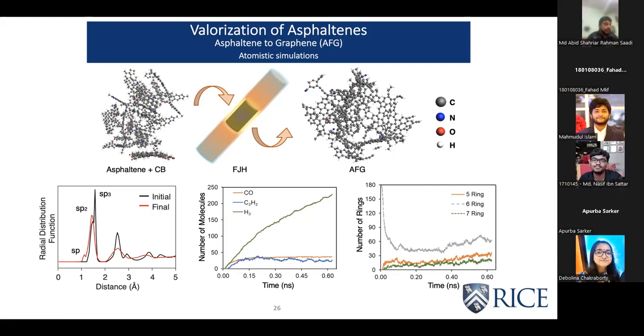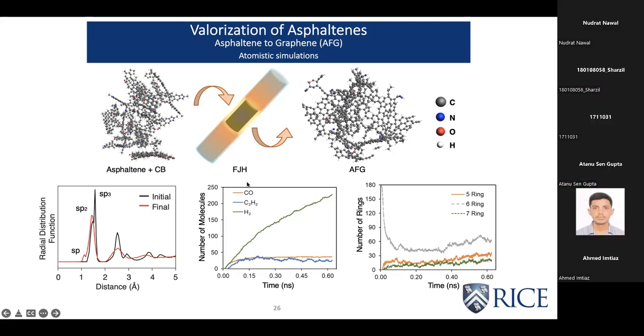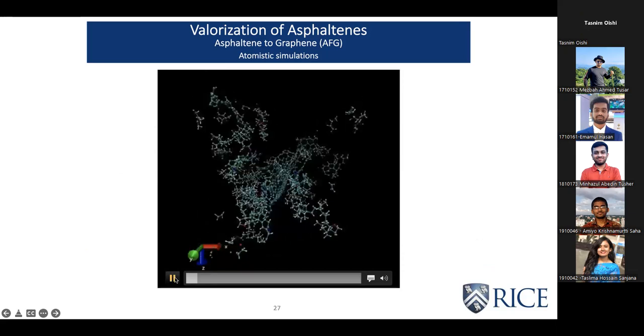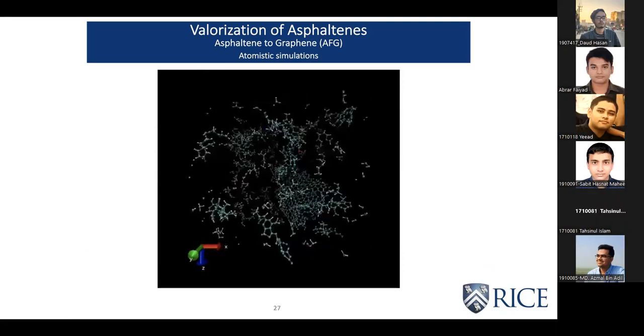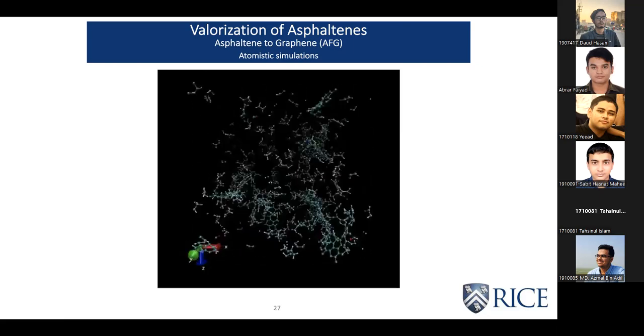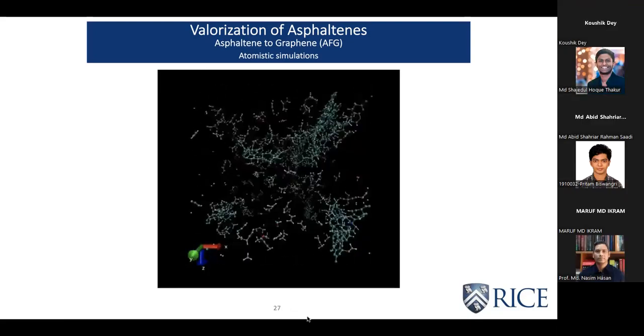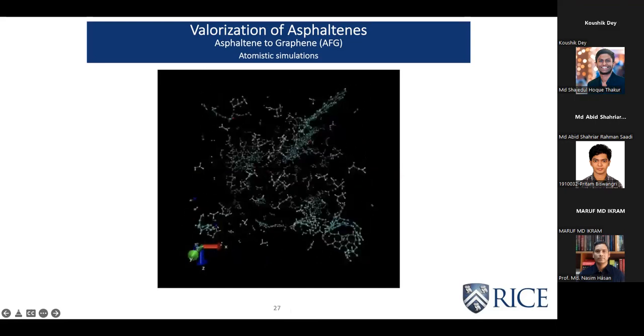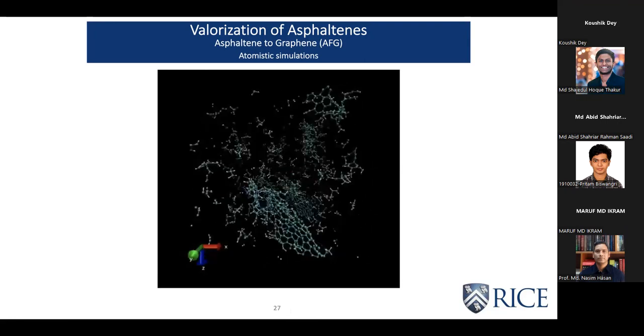So basically, that's why carbon black was added in experiments and also in simulation. In the simulation, I have a video of the simulation. Basically, the asphaltenes and the carbon blacks were mixed together, relaxed, and then the temperature was ramped up to 3000 degrees Celsius, because that's the temperature that one reaches during the flash Joule heating process. And as you will see at the end of the process, we are ending up with some of these ordered graphite-like structures. So here you will see those graphene-like structures.